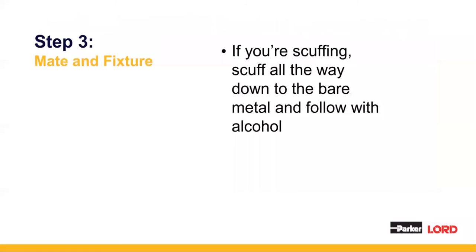Once your parts are prepped, mate and fixture your parts using the same guide as for bonding prior to powder coat, ensuring that you understand the handling strength you need and are clamping your parts long enough to reach the required handling strength. If you do decide to scuff, make sure you scuff all the way down to the bare metal and follow with an alcohol wipe. And then after that, just mate and fixture as usual.